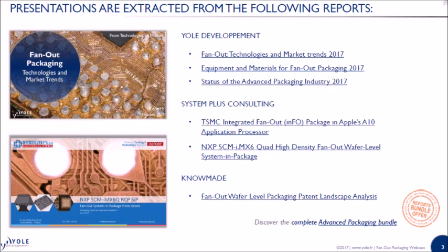Thanks for the question. Actually, it's a very good one. Indeed, quite a lot of people wanted to see if TSMC made a second generation of their InFO package in between the two application processors, A10 and A11. We opened it recently with our partner System Plus Consulting, the company of Stefan, and we didn't see differences in the two packages. So you have potentially different architectures, like different numbers of capacitors, different IPD, but in terms of purely package, it seems to be the same type of package.